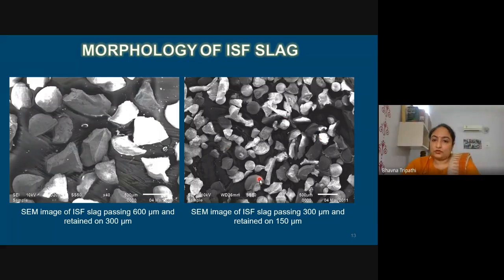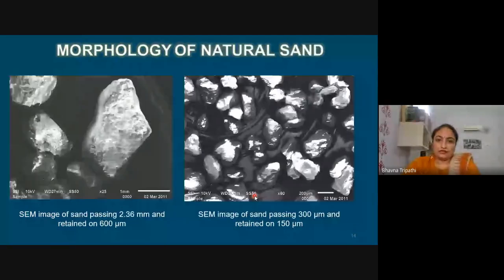Here, if we talk about the particles which are less than 300 micron, we can see a few spherical particles also, which are beneficial for concrete. These are the pictures of natural sand, and as I said, natural sand has all weathered surfaces which are smooth, and this will be the difference between ISF slag and natural sand.